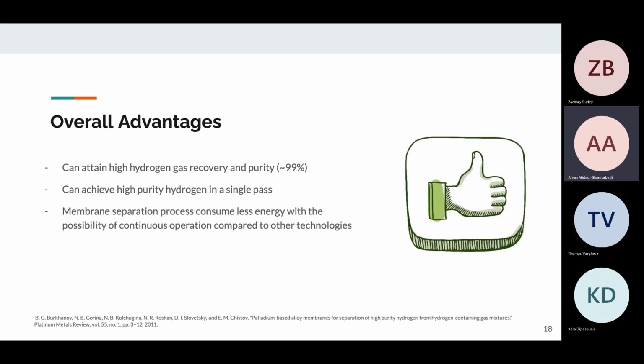To summarize, some overall advantages of using palladium, specifically palladium alloy membranes, for the Alpha Corp scenario include that these membranes are distinguished in terms of hydrogen separation and purification due to their high permeability and selectivity for hydrogen, as they can attain high hydrogen gas recovery and purity up to 99% given the inlet conditions. This can be achieved using a single pass membrane in order to attain this requirement. The overall process is rather simple, given the minimal maintenance and pretreatment needed.